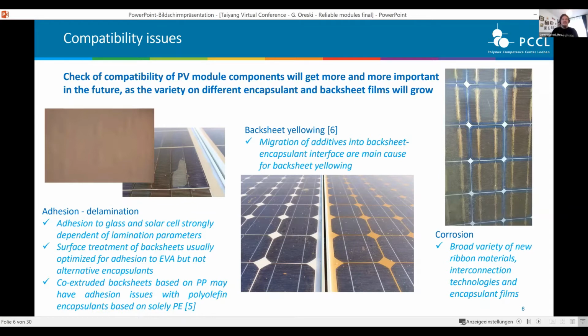And also there are known material incompatibilities. For example, polypropylene and polyethylene don't like each other, so they don't mix, and it's actually quite troublesome to adhere them. And this can be seen, for example, there are already manufacturers of alternative polyolefin-based encapsulants out there. They ask, what kind of backsheet do you intend to use? Or they give this information: okay, we tested our product with these types of backsheets, and here we approve, but please don't use it with this backsheet. So that's a thing that's happening.